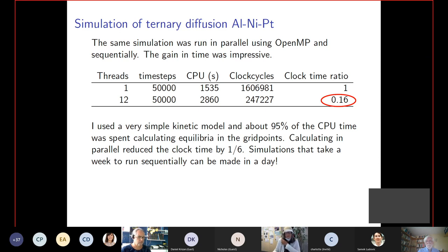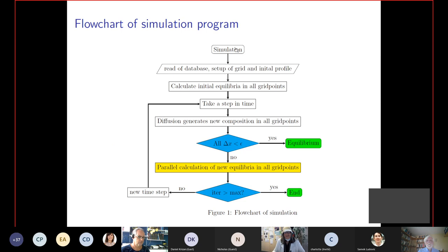And I think OpenCalphad is, for the moment at least, the only software which can do this kind of calculation in parallel. So this is a flowchart of the actual simulation program. You read in the database, set up the grid, and calculate the initial equilibria in all grid points. You take a step in time, you have a diffusion which generates new composition in all grid points. If the change in composition is small, you have reached the equilibrium state. If it is not small, then you can do parallel calculation of all the equilibria in all the grid points. And normally you set a maximum number of steps you want to take. If you have reached the maximum, you stop. Otherwise, you go back, take a new step in time, calculate new diffusion, check if you reach the equilibrium and go on. So this is the loop for the simulation.